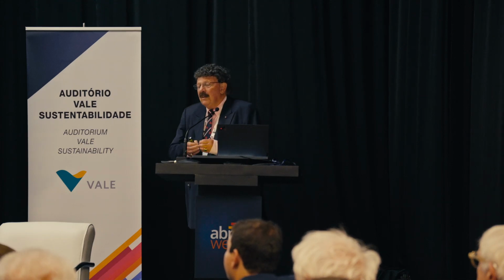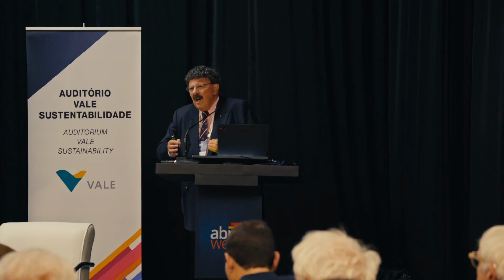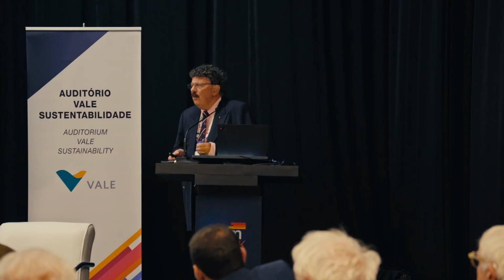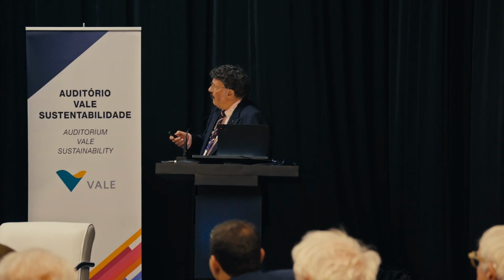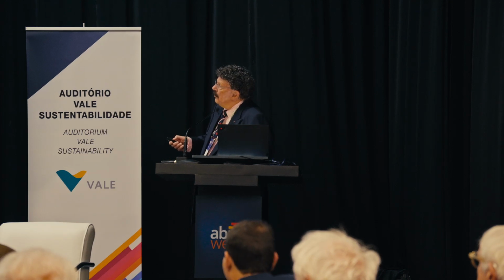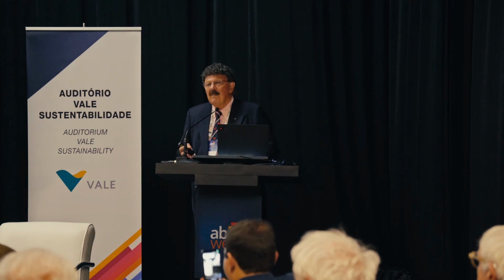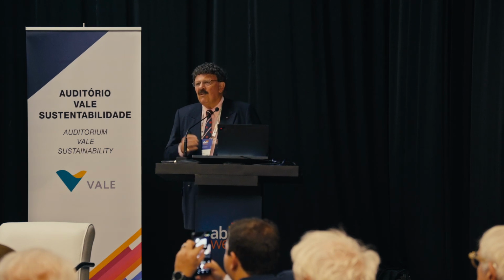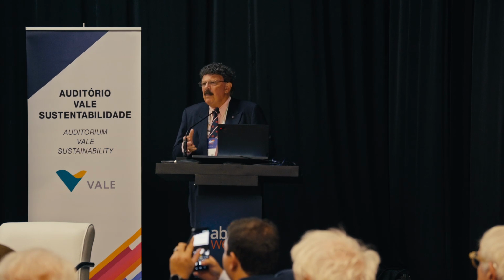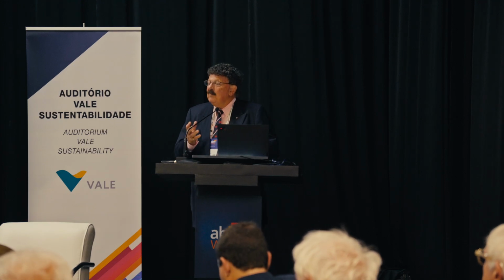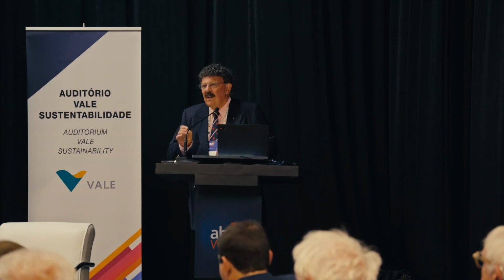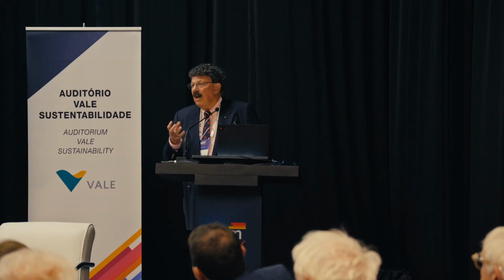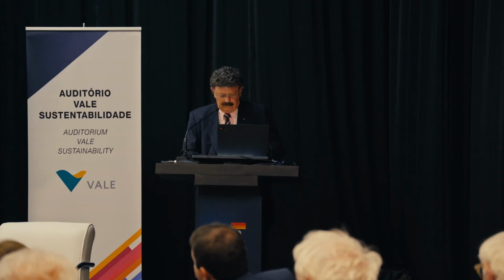So we've got the slip band, which is a hardening mechanism as the dislocations move, but we can see massive cross-slip as well, which is a ductility mechanism. So this is a really magical property where we can get strength and ductility leading to prolonged strain hardening and this really high toughness material.